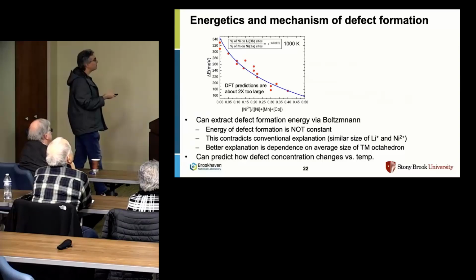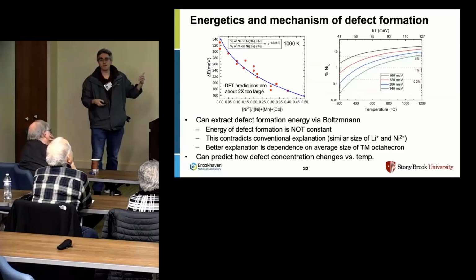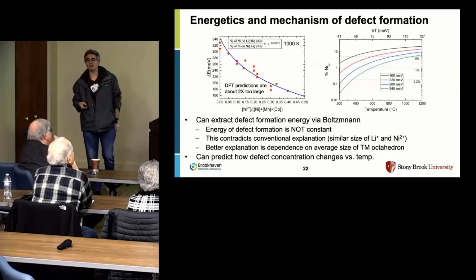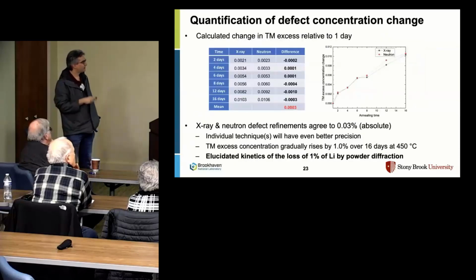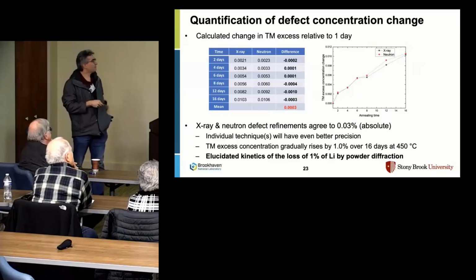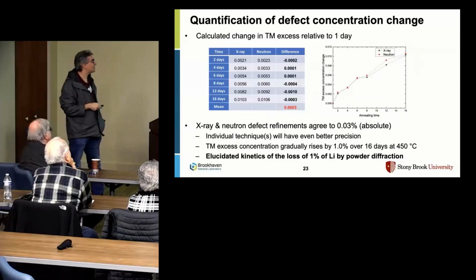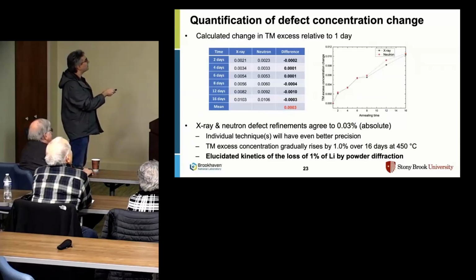And once we have the energies, we can predict the defect concentration versus temperature. So certain compositions have always seemed to have the same defect concentration, but now post-annealing can tune them. So we started doing some of that work. And this is one of my favorite tables. Funny things happen. There are multiple defects involved, not just one, and two of them are active up front in early times.